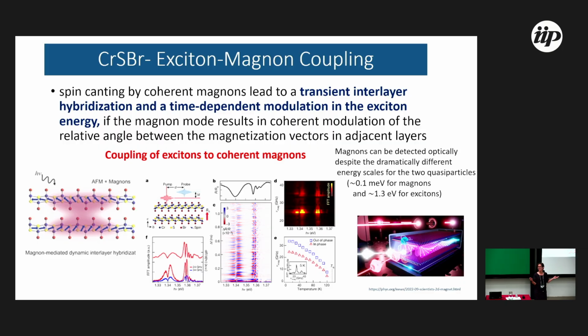And as this conference is about magnons, I put 2 slides about magnons, which is not my work. I just explained that you have this hybridization that appears when you have ferromagnetic order, so you have magnons in this system. The magnon is very coupled with excitons in this system, so the magnons can modulate the energy of excitons because of the property that I just explained. People can show this by using a pump-probe technique, which means you can use a pulsed laser to modify your material, and then probe, for example, the reflectivity. You can control the delay between the pump and the probe, and you can show there are oscillations. You can modulate the energy of excitons, and the frequency of this oscillation is the frequency of magnons.